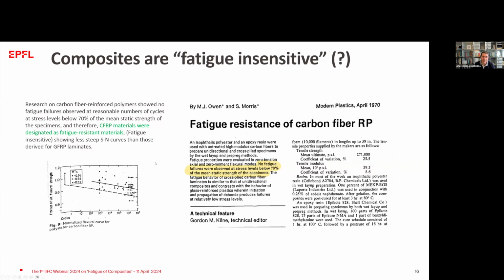And this characterization of composites as fatigue insensitive was given when people started testing carbon fibers. Carbon fibers in the 0 direction show zero or very minimal stiffness drop during loading, and they saw no damage until close to failure. This was also introduced once in the 1980s as the sudden death phenomenon.